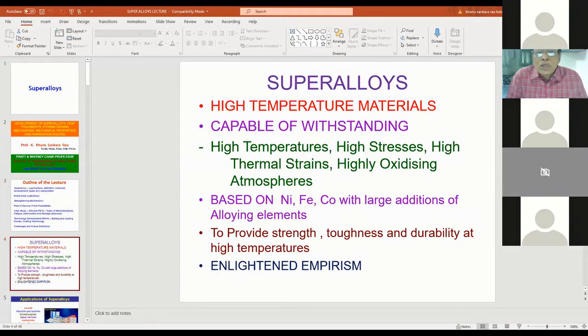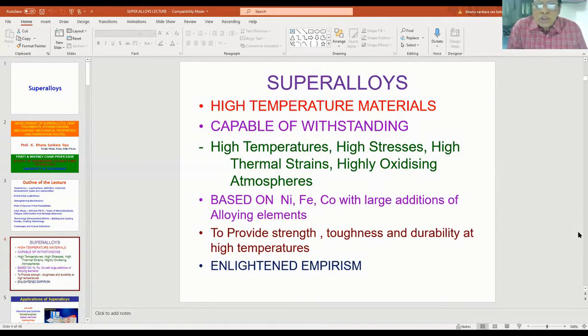Superalloys are an important group of high temperature materials that are capable of withstanding high temperatures, high stresses, high thermal strains, and highly oxidizing atmospheres at elevated temperatures. These superalloys are based on a base. When in the alloy composition the main element exceeds more than 50%, we call it a base. So we have three types of bases, that is nickel base, iron base, and cobalt base superalloys. And these bases will contain some amount of chromium because they have to operate at elevated temperatures where oxidation and other corrosion effects play a very important role. And chromium will be the main alloying element to impart corrosion resistance to the superalloys.